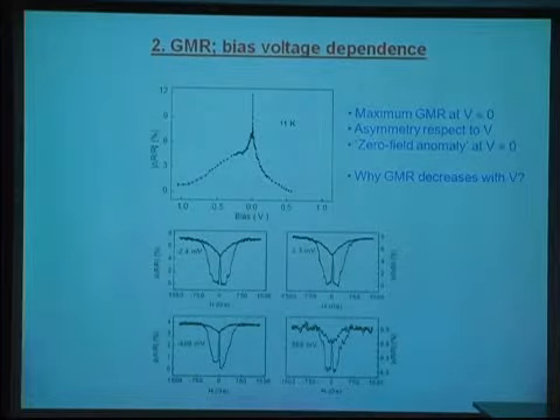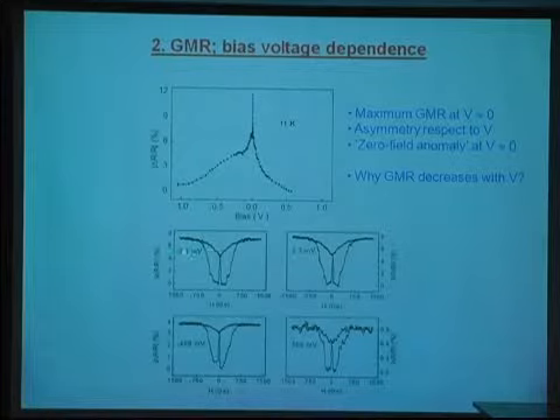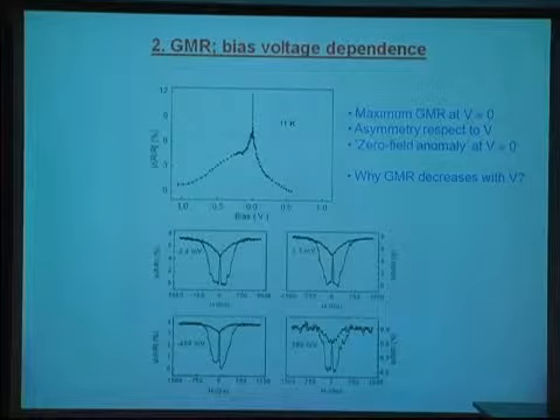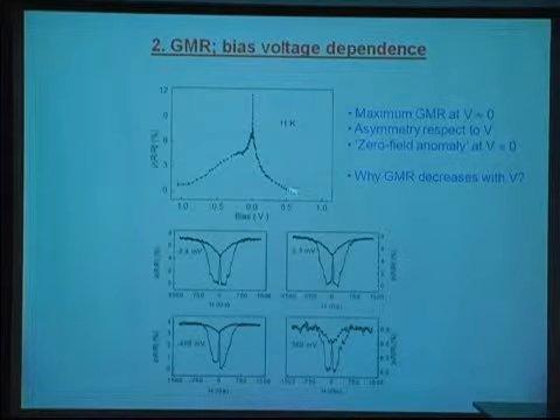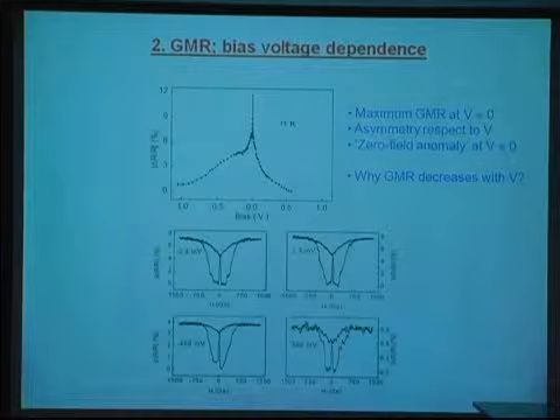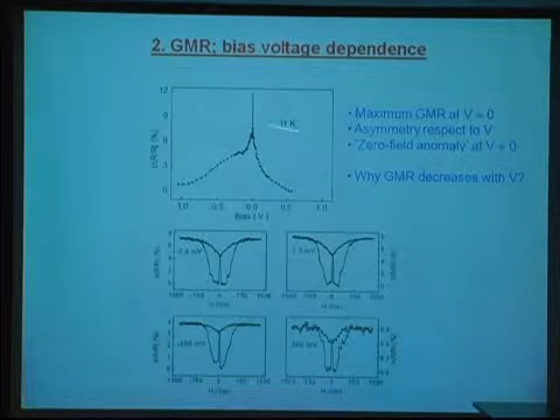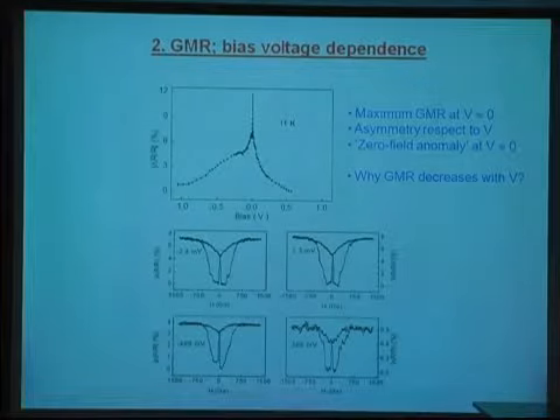Okay, so this is the voltage dependence of the device. You can see here, this is 2.4 millivolts, where the effect is 7%. If you go to 380 millivolts, the effect here is less than 1%, which means the larger the applied voltage, the smaller the magnetoresistance. And this is the profile. It's asymmetric, and we have a very large magnetoresistance at zero applied voltage. The reason for this is still under debate.